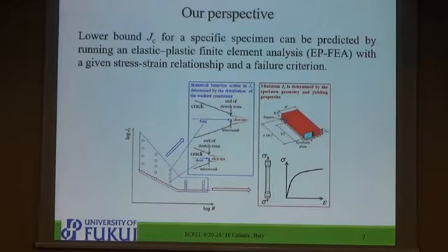We first sought to re-examine Chen's opinion that it is necessary to distinguish the concept of the minimum toughness, or the lower boundary of toughness values, from that of the scatter band of toughness. The former is a definite parameter determined by the specimen geometry and yielding properties, and the latter is a statistical behavior determined by the distribution of the weakest constituent.